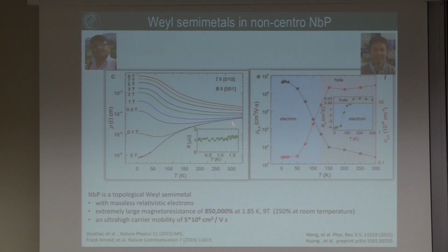Here you see already a significant magnetoresistance effect at room temperature. So you can calculate the mobility, and you see what you expect for a semi-metal, that you have a change from electron to hole conductivity.